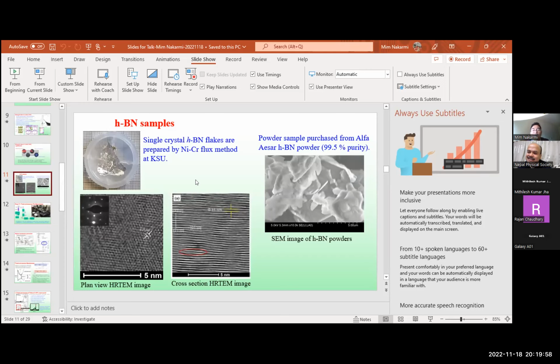No, to make the TEM sample, we have to stick even a small flake on another substrate. It sticks on the substrate, and then we have to cut it down to a very thin sample, because the size of the sample before we can put it into the TEM holder is 3 millimeter diameter, and the thickness has to be in the nanometer range.